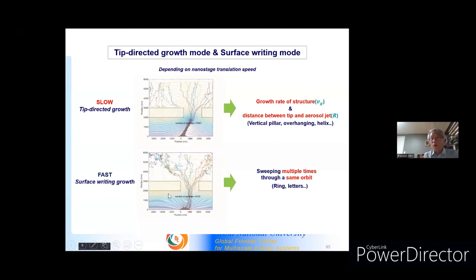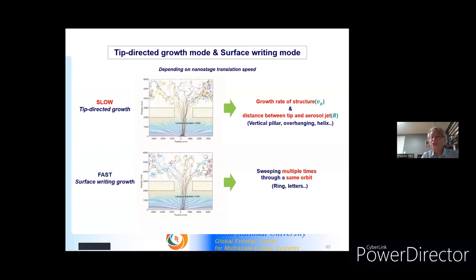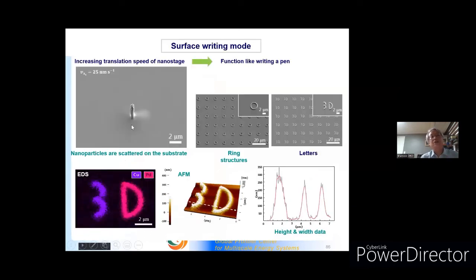Focusing still exists, but for the fast moving case it results in surface writing. This is tip growth mode, but if you move the stage very fast, 25 nanometers per second, particles do not deposit on the top of the structure, they deposit on the surface of the substrate. Using this writing mode, it functions like writing with a pen, making ring structures or letter structures. So our technique has two different modes: tip-directed growth mode and writing mode.